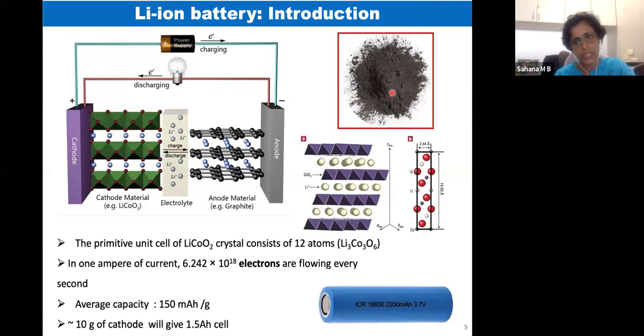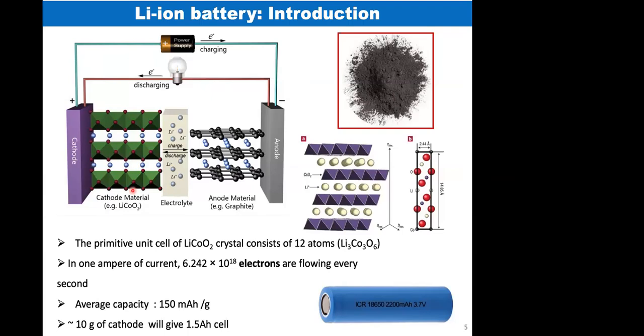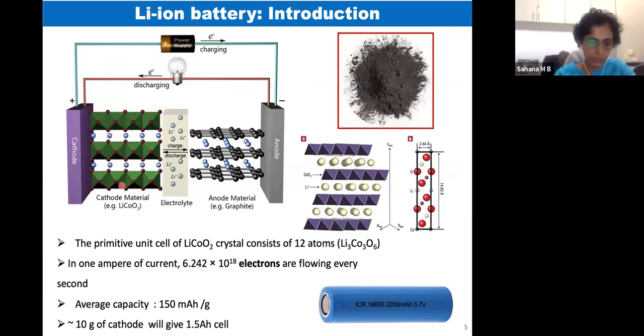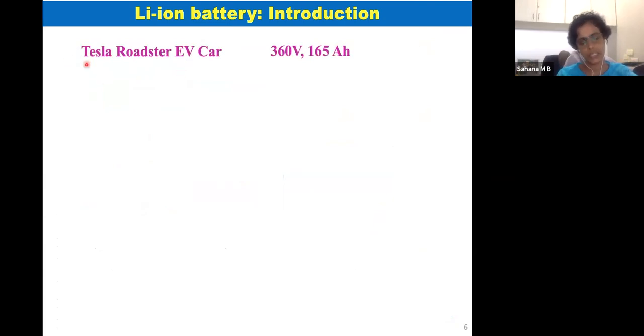Now let's see, by increasing this material, both cathode and anode material, we can increase the total capacity of the cell. Now, whether you take 1 unit cell or 10 gram of the material, voltage is always constant. Voltage is basically the chemical potential difference of lithium between the cathode and the anode. So in this kind of configuration, the voltage you can get is around 3.7 volts. That is the average voltage. And if you see the Tesla Roadster electric vehicle, the voltage it has is around 360 volts and the capacity is 165 ampere hours. That means it should be able to give 165 ampere current for 1 full hour.